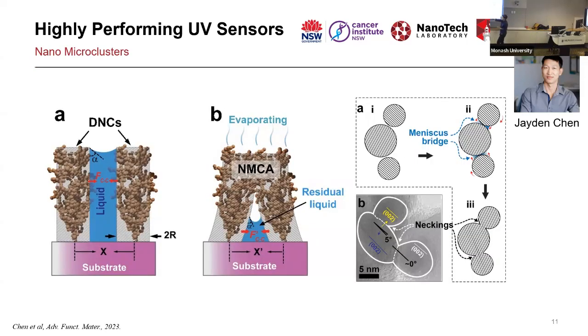This is what happens in the macro scale, but in the nanoscale, the same thing happens. Let's say there are nanoparticles, and because they are made by flame, they just move based on Brownian motion. When they sit on the substrate, there is no significant contact between the nanoparticles. They just sit physically on top of each other. When you want to test them as a sensor, the electron cannot easily move from one particle to the other because there is a boundary here. That's why every time we make the film, we have to put it in the oven and do the annealing to make sure that necking happens between the particles. But with this technique, we don't even need to do the annealing anymore.